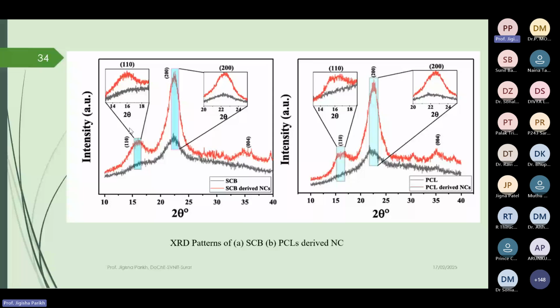So here it has been compared that this black refers to the biomass, that is sugarcane bagasse, and here you can see that with this 110 plane, the crystallinity has increased. Similarly here on the 200 plane, because it is a three-dimensional material, different planes have been identified, and this crystallinity index has been shown over here. Similarly with the PCL, here you can see the crystallinity index has increased, and here also. So we have received a very good increase in crystallinity index, because this is very important if we want to use it as a nanofiller or additive in polymer composites. If it is not crystalline material, then it is not useful for that particular application, and hence we have to identify this index through the XRD measurement.